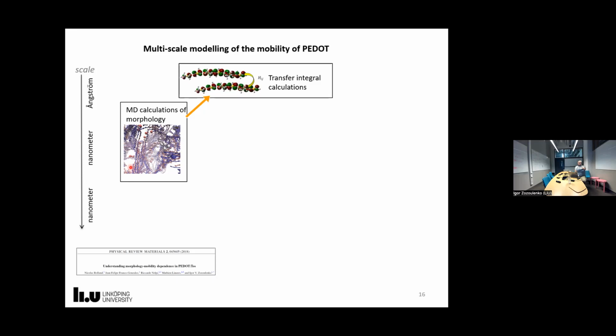Then we need to calculate the hopping of polarons from one chain to another chain. This means we need to perform calculations of these hopping probabilities, or let's say transfer integral calculations. These are at the angstrom scale, and you typically use a density functional approach. Also, we need some information about the structure of the density of states, so you also need to do some calculations of the density of states.